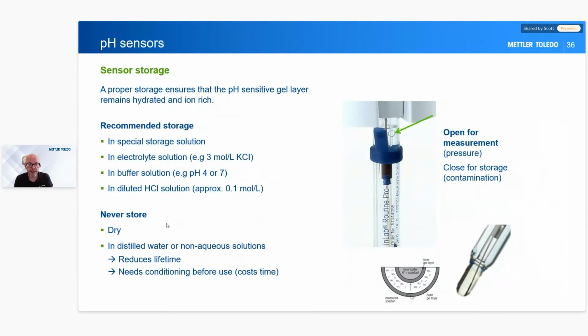So the first thing is storing our pH electrode. When we're storing our pH electrode, what we're trying to do is ensure that the gel layer on the bulb at the bottom of the electrode remains hydrated and ion rich. So we can store it in special storage solution. You can find some from Mettler Toledo and other brands as well. If you don't have special storage solution, the next one is the electrolyte solution that's inside. So the inside here was the electrolyte, and we should store it in that electrolyte.